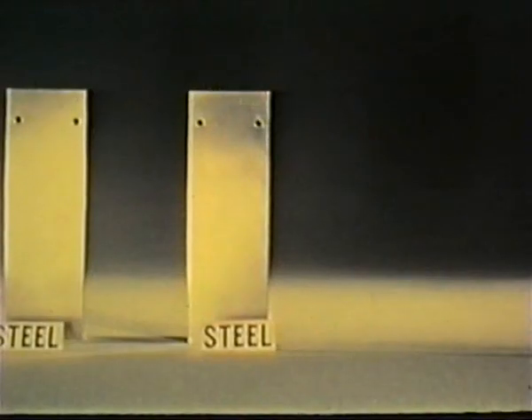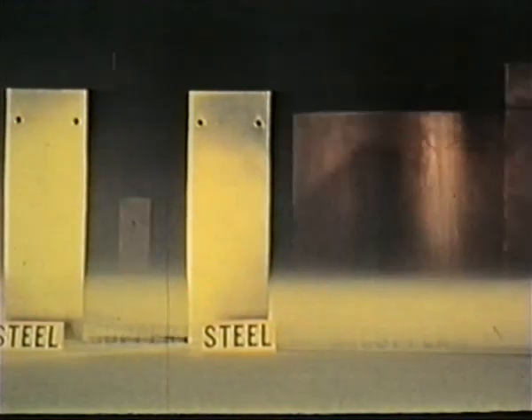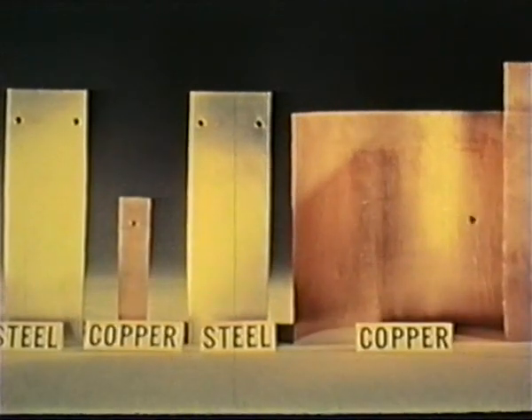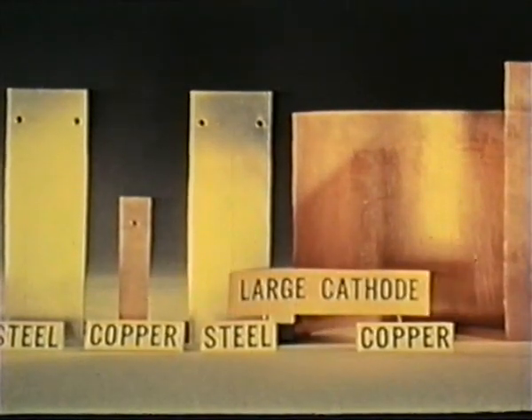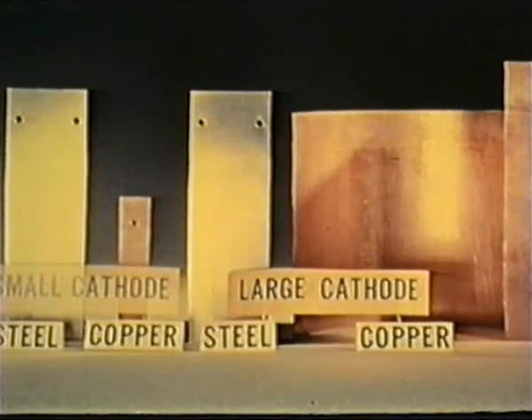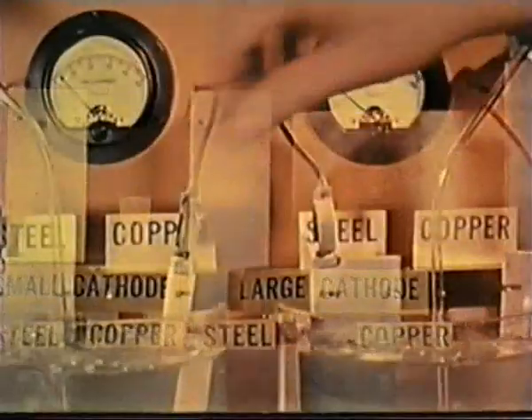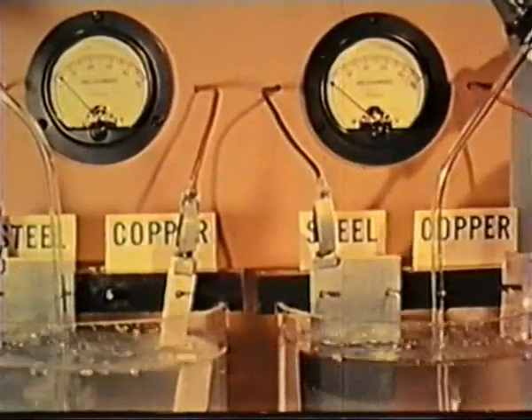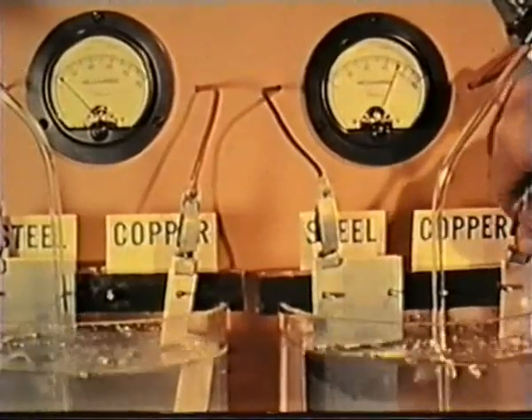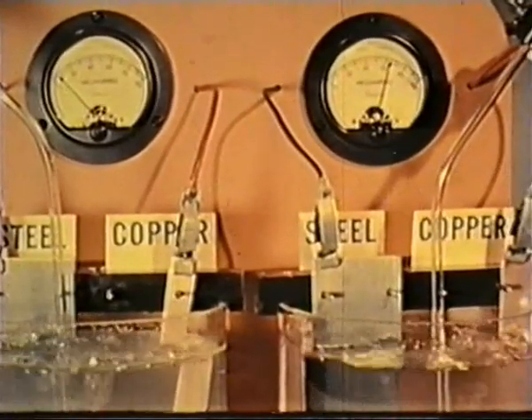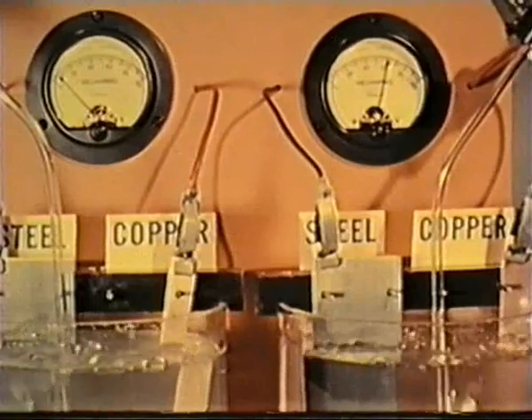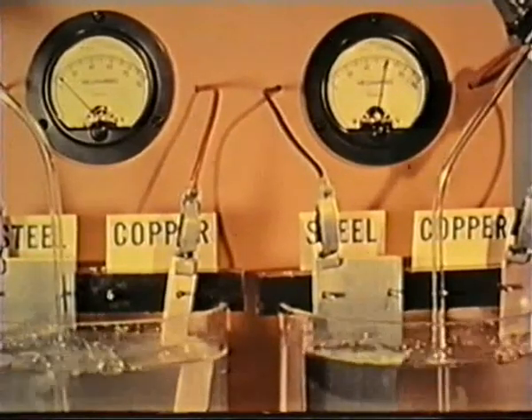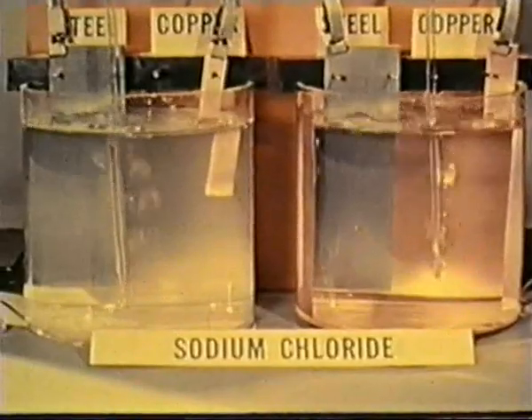A direct example of this effect on galvanic corrosion is provided by an experiment in which pieces of steel of the same size are connected in an aerated salt solution to pieces of copper of different sizes, one large and one small. Both couples generate current, but notice, the couple with the large cathode produces the higher current. Thus we can see that it is hazardous to connect a small anode to a larger cathode. The following experiment further emphasizes this point.